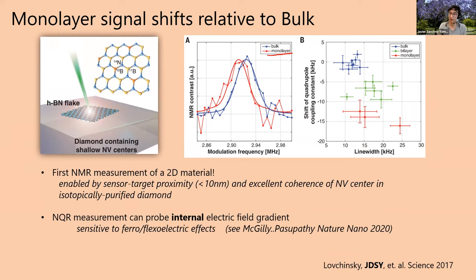This is not so surprising because what we're measuring here is what's known as an NQR signal. This is a shift that's due to the quadrupole resonance of the boron-11 atom, and it's sensitive to electric field gradients inside the material.